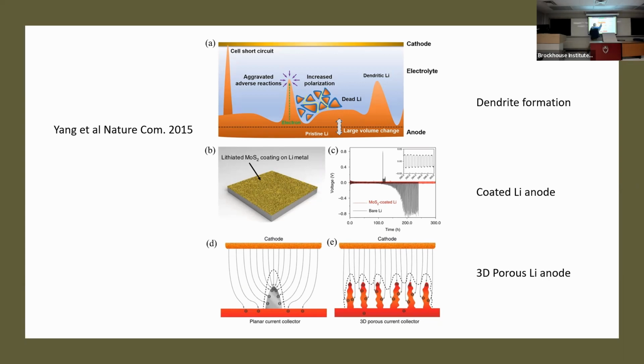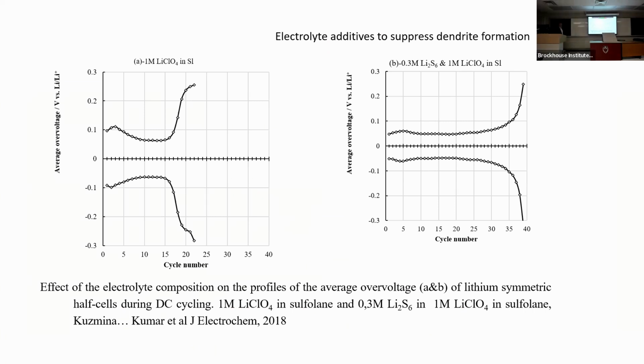And as a result of that, we have to think about various ways by which we do not allow that to take place. One approach that we see in nature is having some kind of interlayer, like a lithiated MoS2 coating, which really seems to work very well. Instead of having one big dendrite forming, there are many dendrites forming, and they never quite reach the cathode. And one can also electrochemically measure this: this is very stable, the dendrites are not forming. When you have this departure, there's a huge overpotential. That means the dendrites are forming.